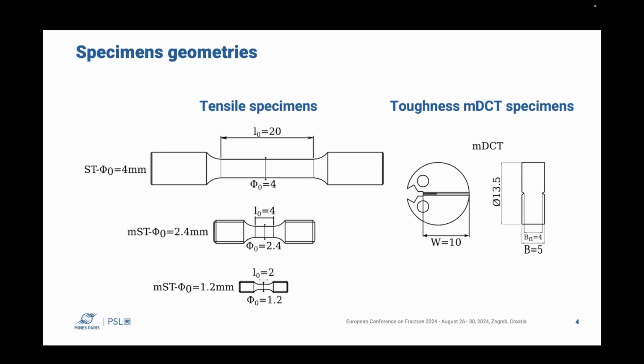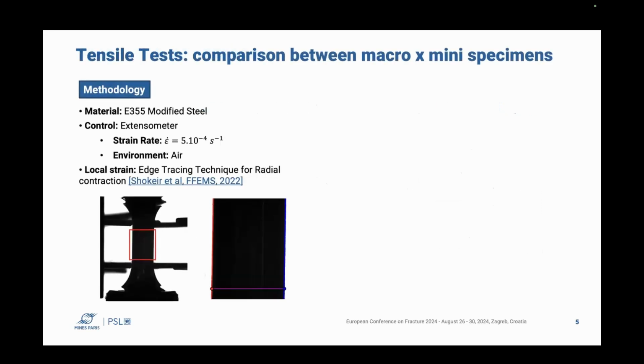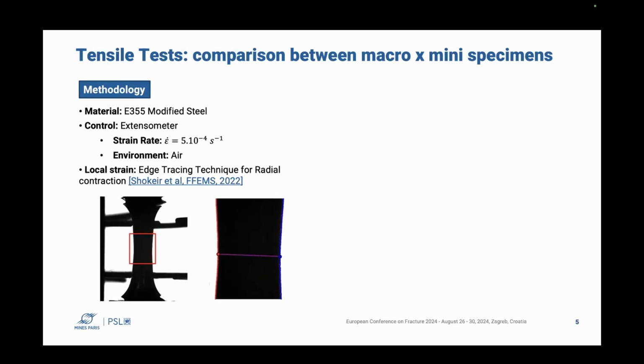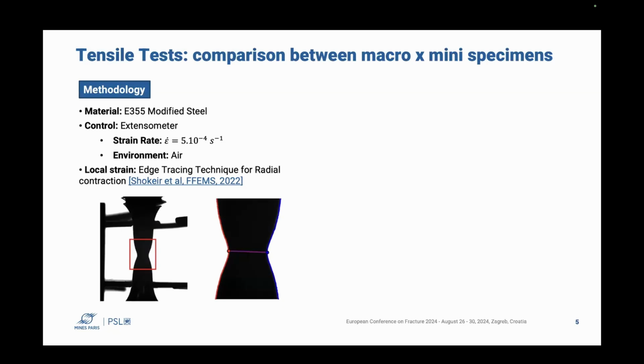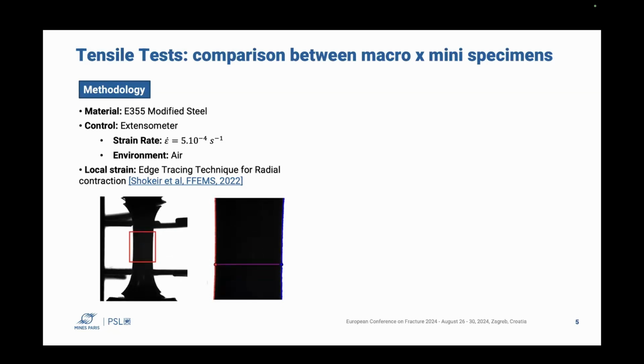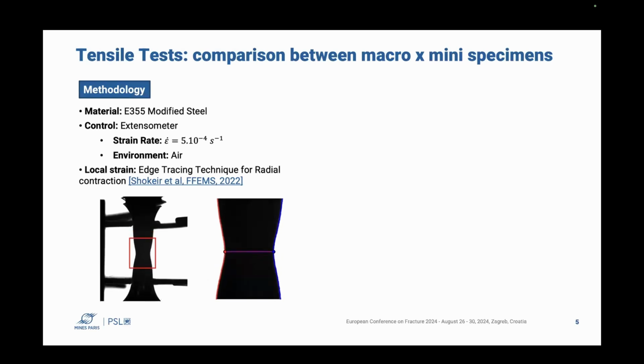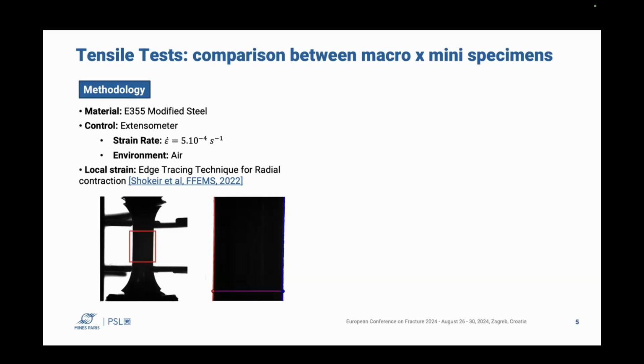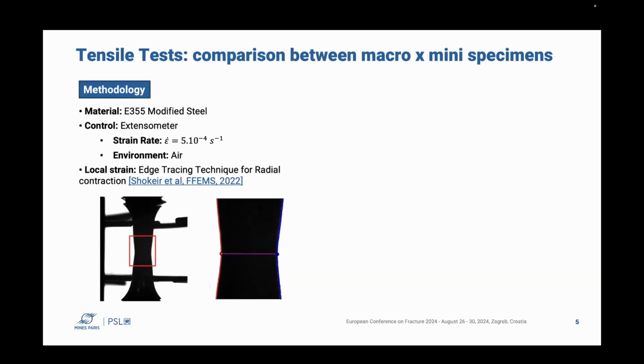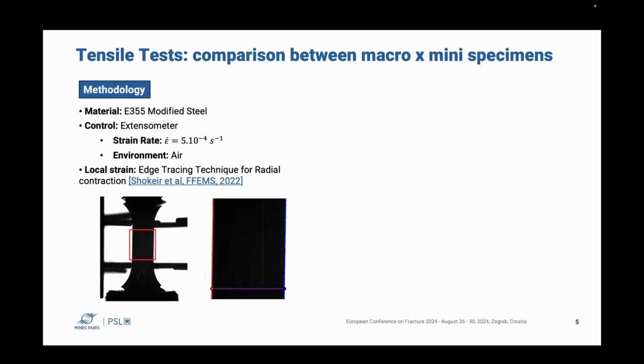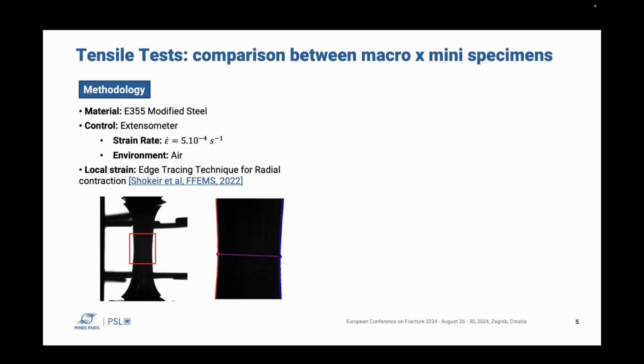I present two geometries of mini tensile specimens with 2.4 millimeters diameter and 4 millimeters of gauge length, and mini specimens with 1.2 millimeters of diameter and 2 millimeters of gauge length. And also the mini toughness specimens that have a width of 10 and a thickness of 5 millimeters. So first of all, to do the validation of the mini size specimens, we performed some tests in the MTS machine with extensometer control, in air. And we follow the local strain, I mean the necking, with the edge tracing technique, where we put a camera and a backlight to follow the contour of the specimen, and so we can have the information of the radial strain.